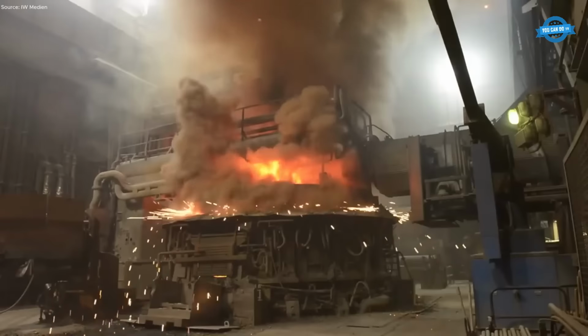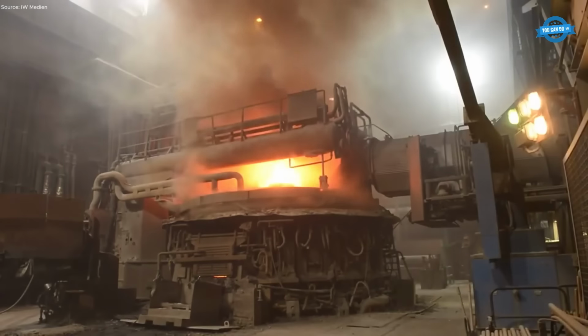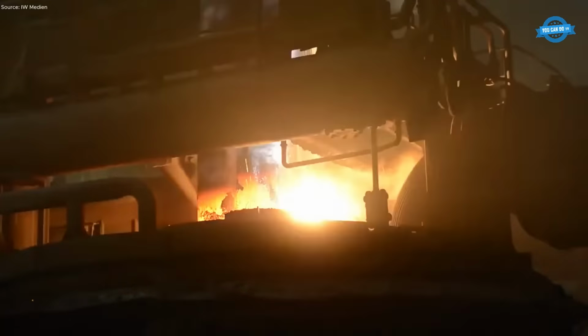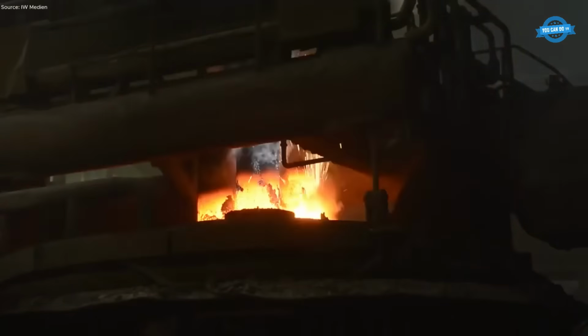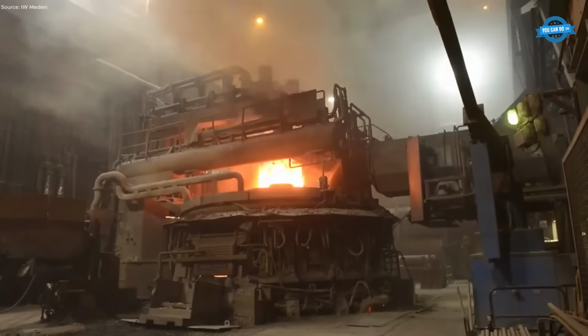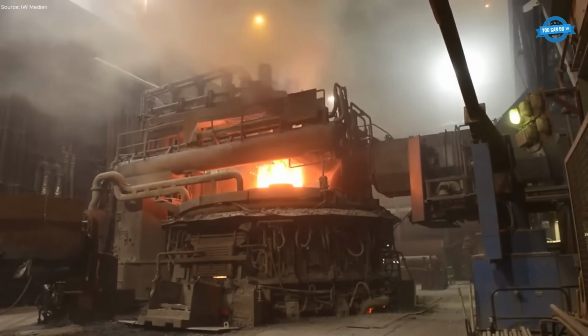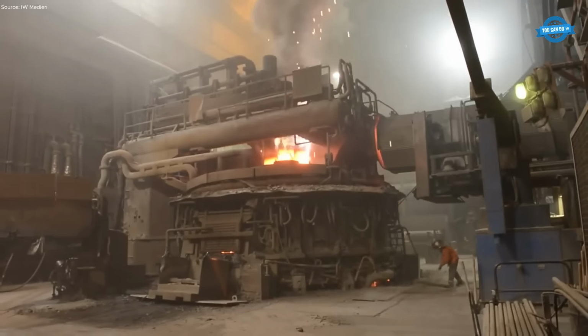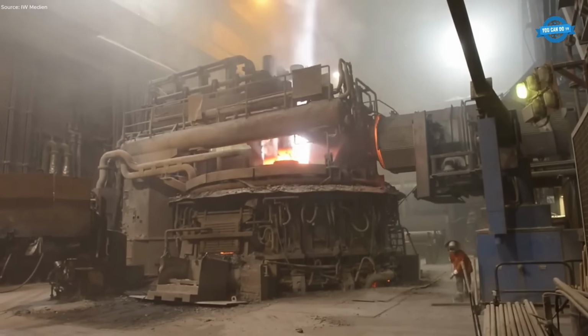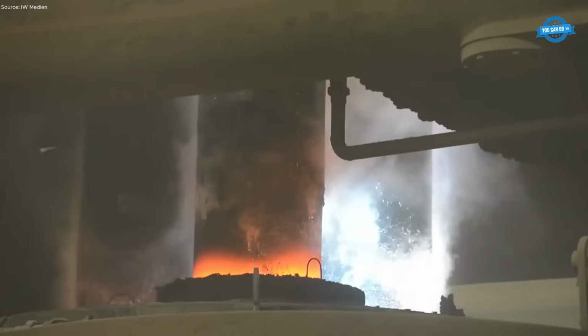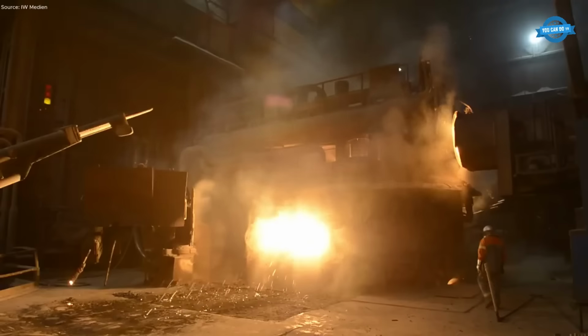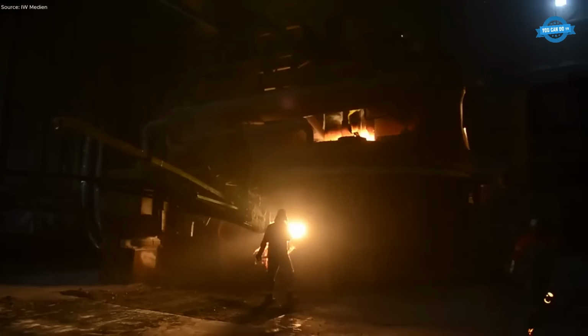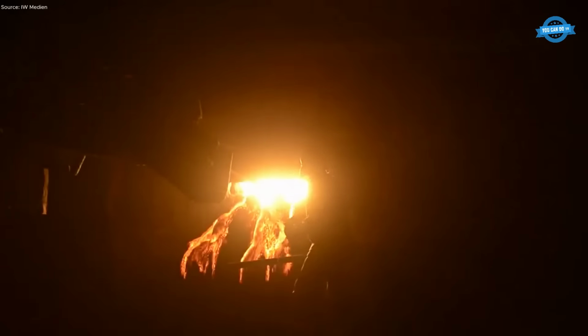Every 90 minutes, operators power up the furnace, unleashing an intense inferno. Temperatures inside soar beyond 1700 degrees Celsius, melting up to 75 tons of material per hour. After tapping the molten steel, the furnace door, still coated in glowing slag, must be cleaned, a task too hot for human hands and handled instead by machines.